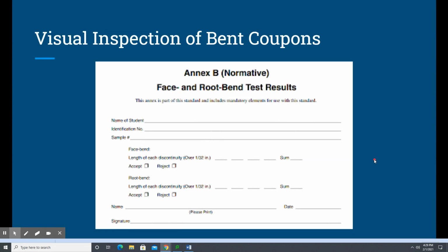So after we evaluate the bend tests, I'd fill out some basic paperwork indicating who welded it, is it acceptable, is it not acceptable for both the face bend and the root bend. One thing I'll point out as far as documentation, I do it before I cut the strips typically, right after visual inspection, we'll take that stamp tool and we'll stamp in which one's going to be the face, which one's going to be the root. So after we put the lines on there for cutting, we know where the bend tests are taken out of, and we'll stamp them. We'll stamp them with 2G or 3G, depending on what position they were welded in. We'll stamp them with the student initials, and we'll stamp one on the face side and one on the root side so we know which bend it was. That way we're kind of keeping things separate.